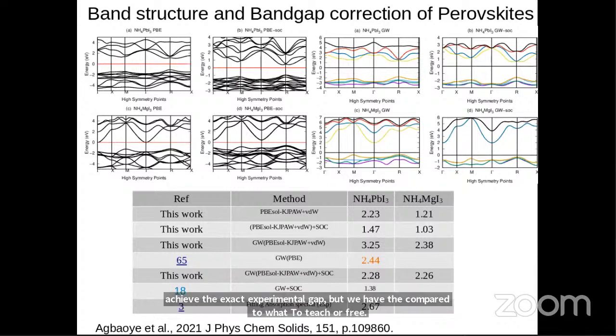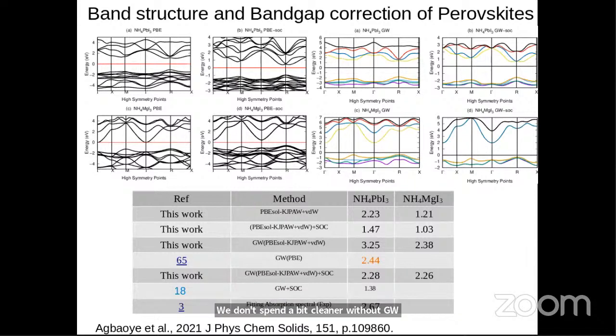without spin-orbit coupling and without GW, and compared to what GW alone is doing. So here we are trying to use GW and also merge with spin-orbit coupling such that we are able to achieve a very good band gap. So here we have the band structure of methylammonium lead iodide for DFT and GW.